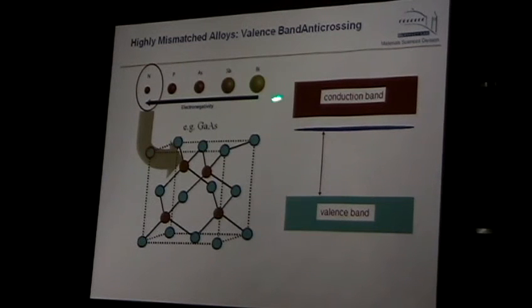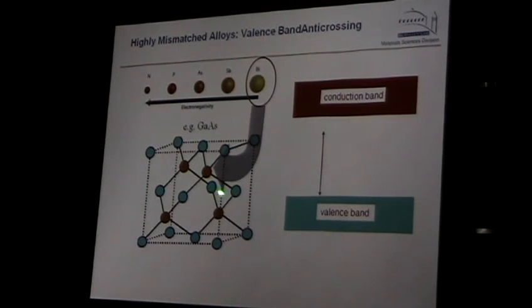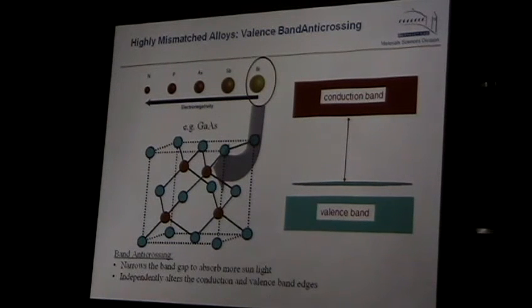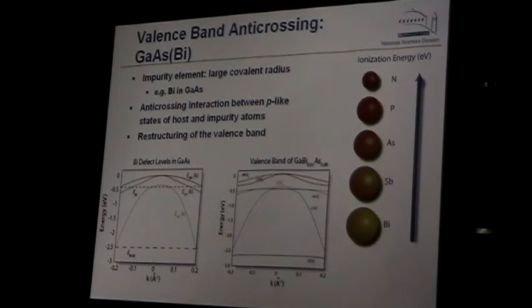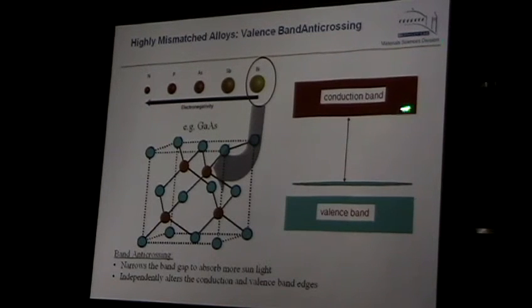However, we could put bismuth, which is very large and very different from arsenic as well, on the arsenic side. And then we form a band, as I mentioned, here. So we can control what's happening around the conduction band and around the valence band by choosing what we substitute. Or you can put even both of them, and then you can produce narrow bands here and there. An advantage of putting both of them is that you can make it lattice matched to gallium arsenide if you put them in the proper ratio.